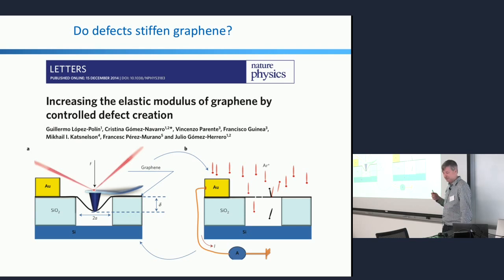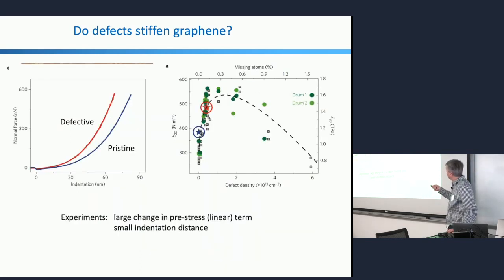So I just wanted to mention that there have been a few papers talking about mechanics of graphene and other 2D materials that have come up with some rather counterintuitive results, and this is one of them. This is in Nature Physics just 3 years ago now, and the claim is that if you take one of these membranes and bombard it with argon, so introducing defects in a different way than we did, using argon rather than oxygen, you actually stiffen the material. The experimental argument was that the stress-strain curve goes from pristine like this. When you make it defective, it's steeper, and if you do this linear plus cubic fit and pull out the Young's modulus, it goes up, and it goes up by a lot. If you start here, it goes up and almost doubles, and then starts to come down again as you get more and more defects, right?